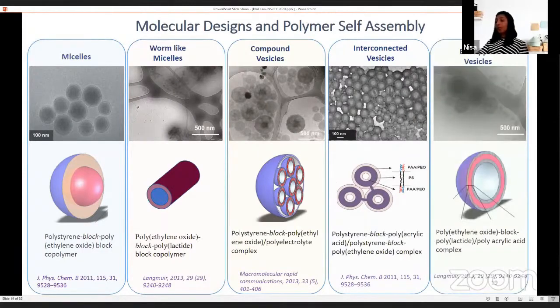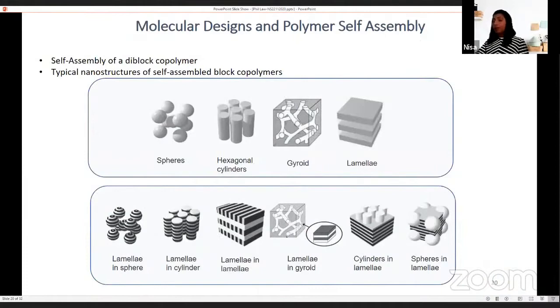Another morphology we developed is a vesicle that is called an entrapped vesicle. That is, you can see one vesicle is entrapped in another vesicle. We used various combinations of block polymers for the design of these nanostructures. These block polymers can also form these nanostructures in their solid state. These are the major nanostructures they form in their solid state. In addition to this, they can also form hierarchical structures such as sphere in lamellae, lamellae in lamellae, etc.